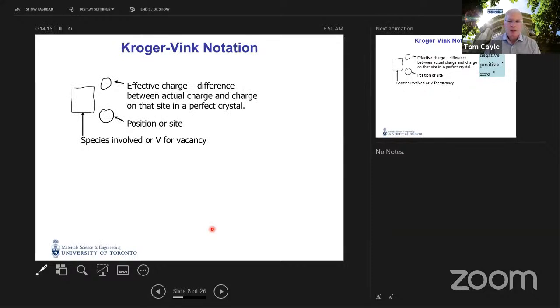In order to try and keep track of that, there's a very useful notation known as Kroger-Vink notation that allows us in a very compact way to describe what species, what atom or ion, we are talking about. Or if we're talking about a vacancy, then we use the letter V. The superscript represents the effective charge. So this isn't the nominal charge on the ion, but rather the difference between the charge that would be on that site in the perfect crystal and the charge represented by the species that's actually present on that lattice site. And then the subscript here describes the position within the lattice that we're actually talking about.